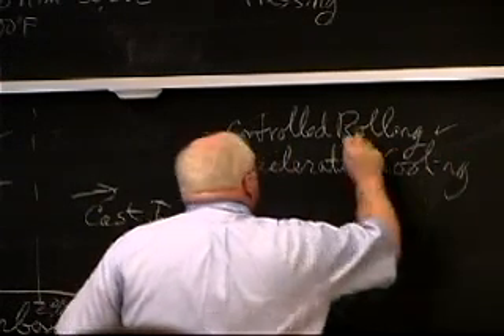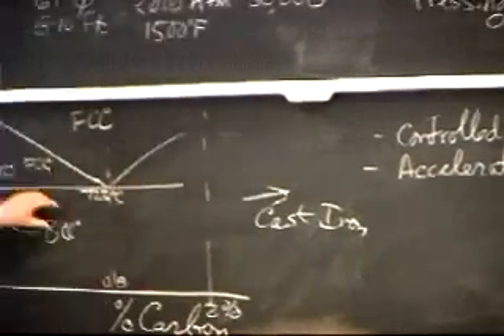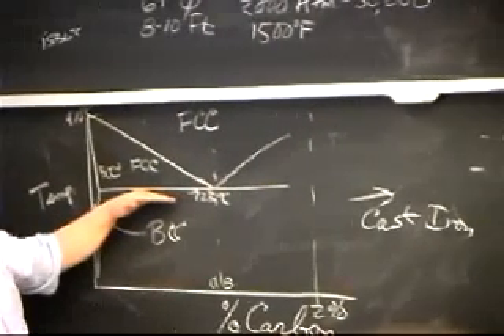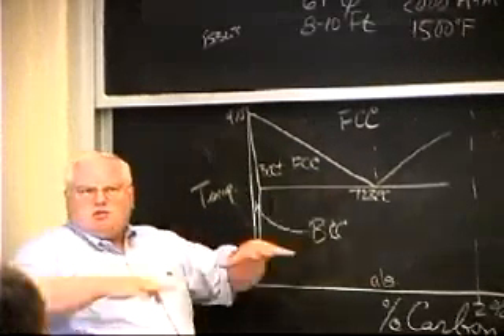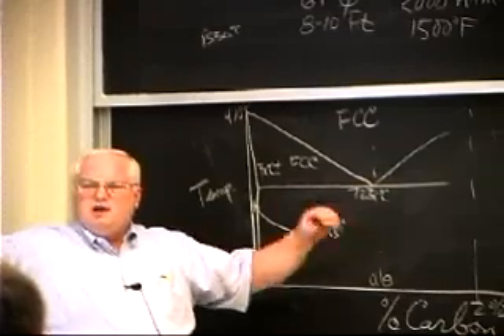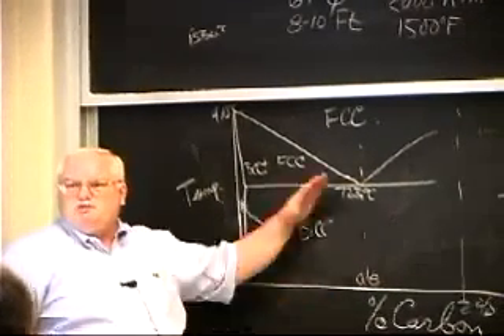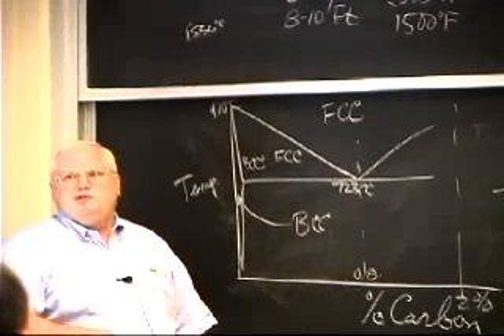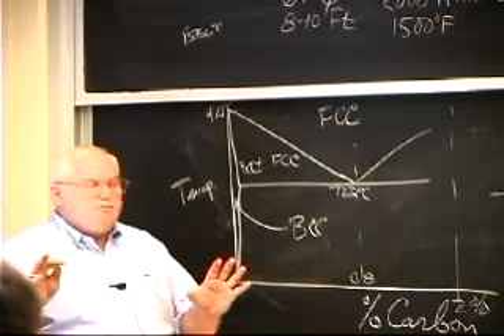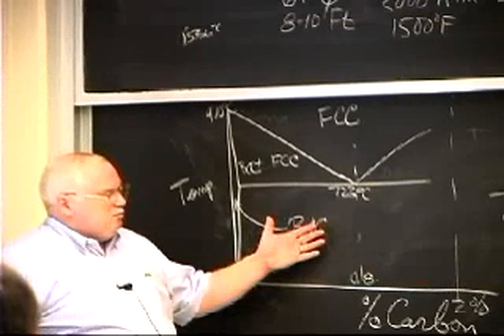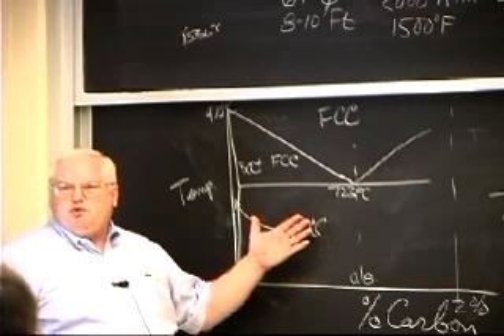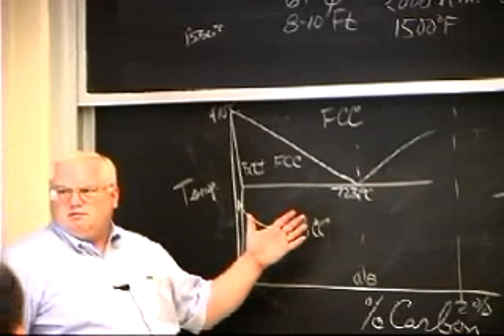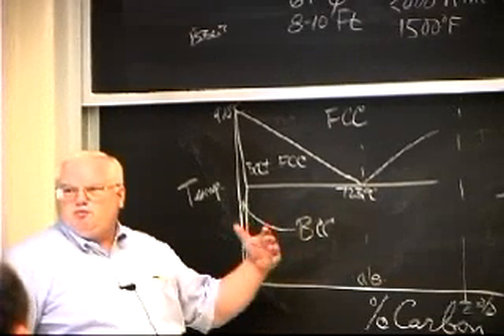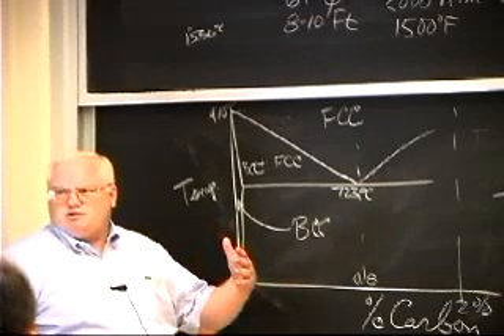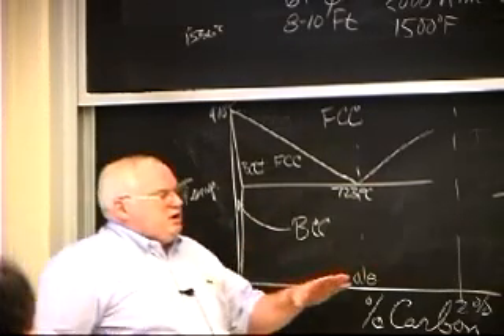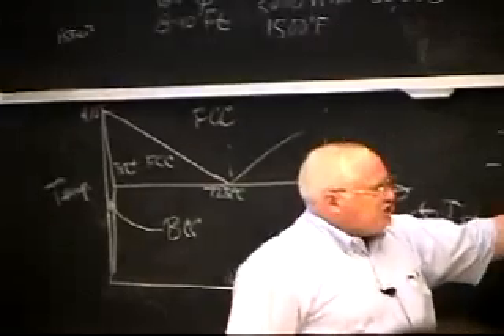Accelerated cooling may or may not make use of deformation up here, but rather than just letting the stuff cool down in the air, they actually built whole lines where they would spray water on the plate to cool it down more quickly. Now, you don't hose it down, you have to have a nice uniform stream, and you have to be very careful because if you don't do it properly, you end up with a pretzel rather than a flat plate. Because you're going to cool the steel more quickly on the surface, you're going to have tremendous residual stresses. And so in the early 80s, the Japanese started doing this.